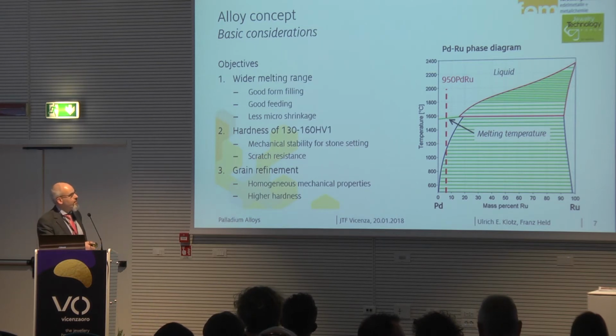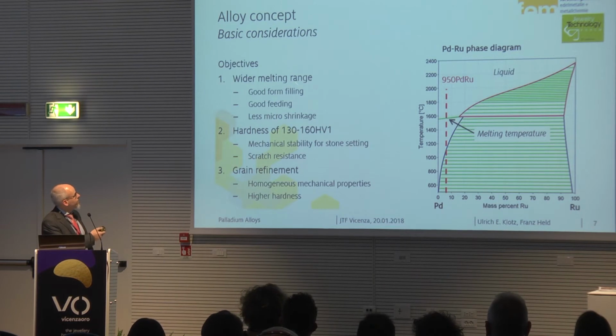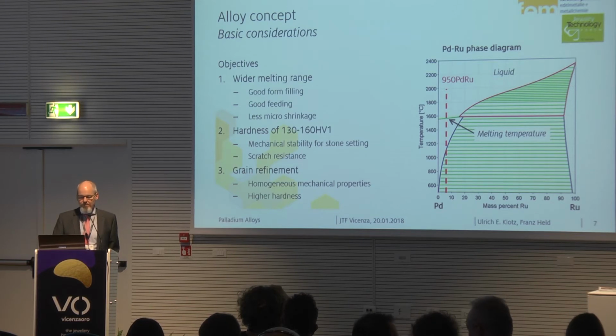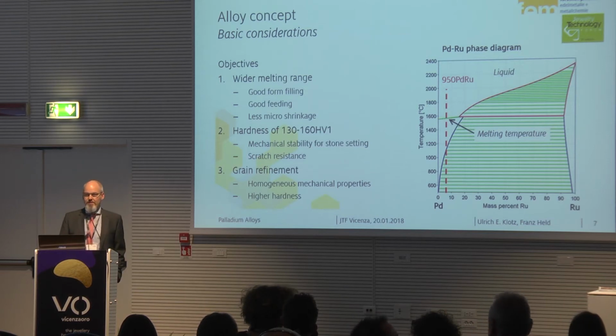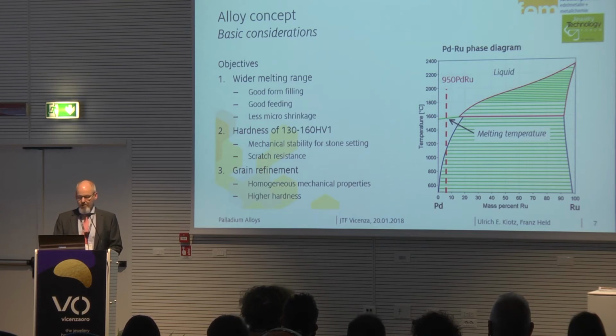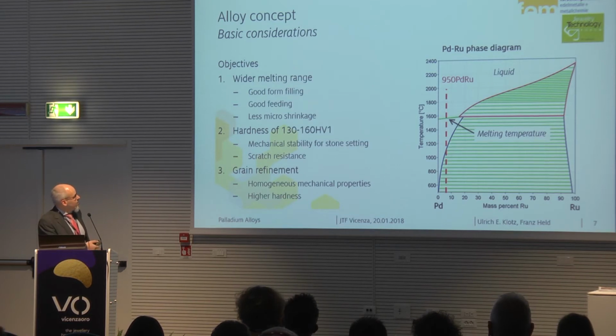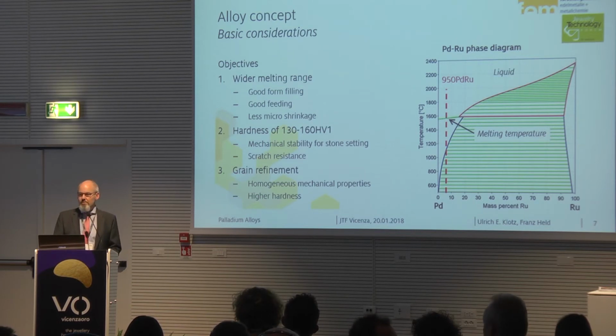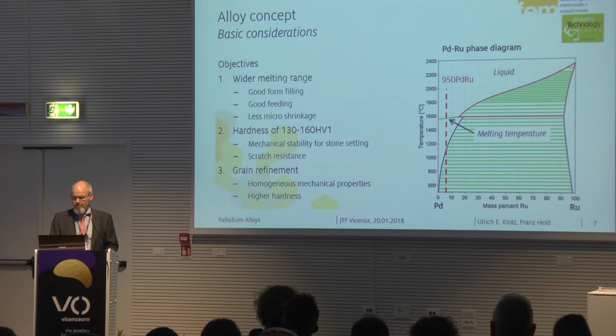Now, our objective was to have a form filling and feeding and micro shrinkage which is at least comparable to 950 palladium ruthenium, but the hardness should be in the range of 130 to 160 Vickers, which is an established value for palladium alloys with good properties. This provides suitable stability. We also want to have a certain grain refinement to get fine grain structures which have more homogeneous properties and also higher hardness.